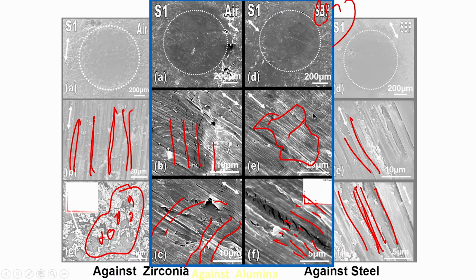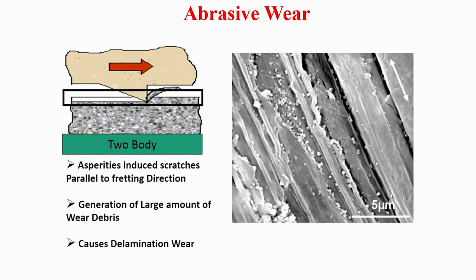And this is what happens when you do the test against alumina as a counter body. In case of alumina, again there are signs of abrasive wear, but certainly some of the signatures of very severe wear as in case of steel were not found after the test with alumina.